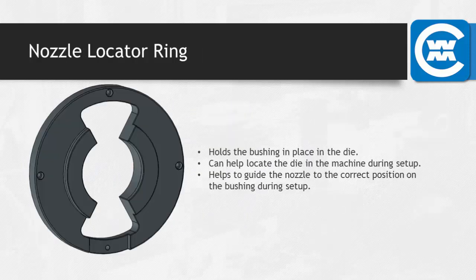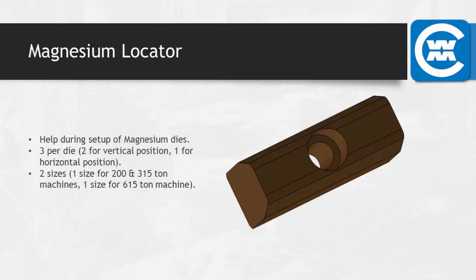The nozzle locator ring, as the name implies, is there to align the nozzle to the bushing for a perfect fit, and that allows no metal to leak from the nozzle or the bushing while the shot is being made under high pressure. Magnesium locator: unlike hot chamber dies, the cold chamber die has a shot well that sticks out of